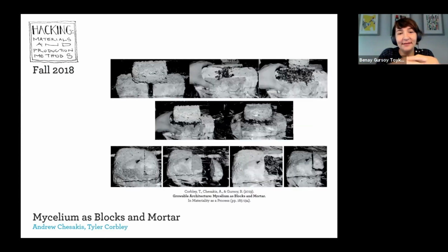So they made some tests exploring using mycelium as the mortar between the blocks, but also they on purpose impaired the block itself, and then used mycelium to see if mycelium can repair it by growing in between the different parts of the block. So this is actually how it all started. And they also presented their explorations in a symposium in Lisbon. So that was also their first experience presenting as undergrads in an academic symposium, and they enjoyed this.